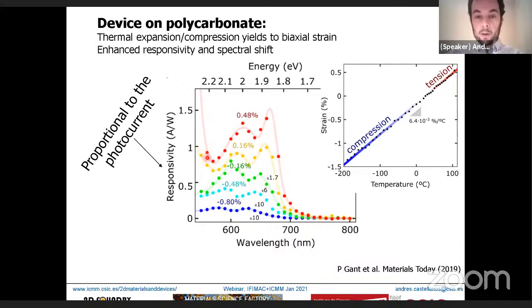So what we see in our spectra is that these spectra have two peaks here, which correspond to these two excitonic features. And we can change, so what we see here are the strain values we are applying, from plus 0.5% tension to minus 0.8% compression.